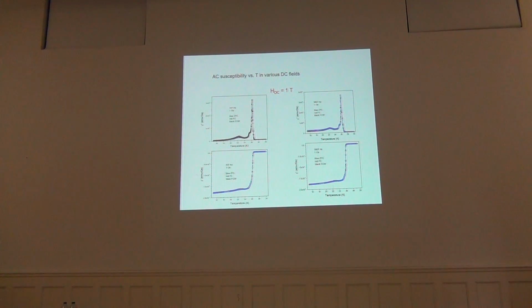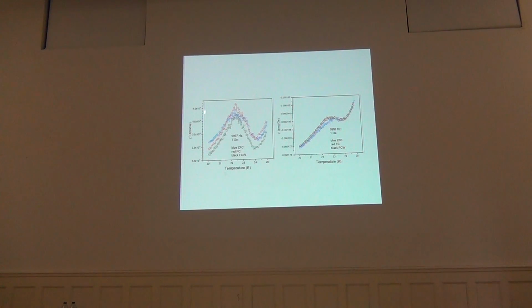This one was a little bit more intriguing, in the in-phase susceptibility measurement, which means the diamagnetic signal of the single crystals. So you see this is the 1 Oersted excitation. In the previous measurement for the vortex glass study, we had to go to much lower amplitudes to have low probing currents. In this case, we used higher excitations, and this is a zoom of that anomaly which I showed. So we have zero field cooling, and after that field cooled, the warming. So we see also the irreversibilities in the vortex dynamics in the single crystal.